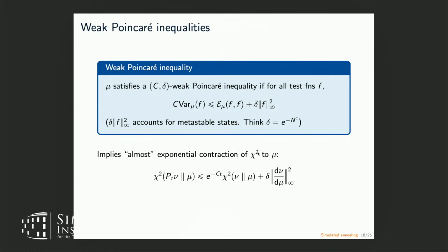Then just like how a Poincare inequality implies rapid or exponential contraction of chi-squared, a weak Poincare inequality will imply this sort of almost exponential contraction. So you'll exponentially contract, but you'll bottom out at some value that isn't zero. And this thing you bottom out at will depend on delta and on the likelihood ratio between your initialization and the target. So the upshot of this is that if you initialize at a warm enough start, which we'll take to be a measure whose L infinity norm likelihood ratio with the target is not too big, then you mix rapidly up to a small error.